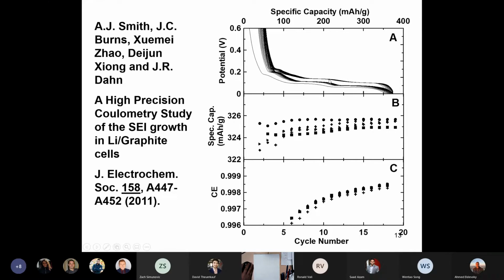And then you recharge and you come back to the top, and there's some irreversible capacity. That corresponds to some lithium atoms that were used in the SEI. But then every subsequent charge-discharge cycle that you take, the total irreversible capacity gets bigger and bigger and bigger. And you can see by the way these lines get closer and closer and closer that the rate of increase of irreversible capacity gets smaller and smaller. And you can also see that the shift in the delithiated state and the shift in the lithiated state are exactly the same.